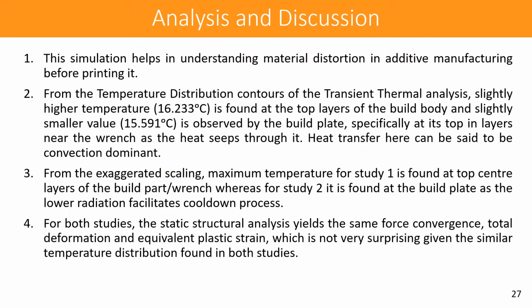This simulation study helps in understanding material distortion in additive manufacturing before printing it. That is a huge all-around benefit. From the temperature distribution contours of the transient thermal analysis, slightly higher temperature is found at the top layer of the built body and slightly smaller values of 15.5 degrees Celsius are observed by the build plate.